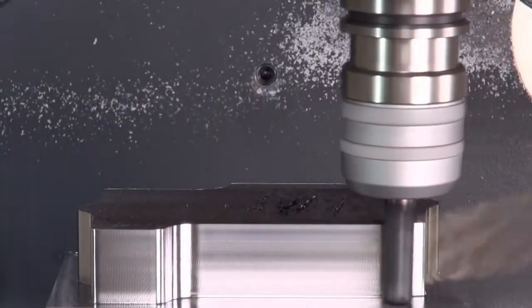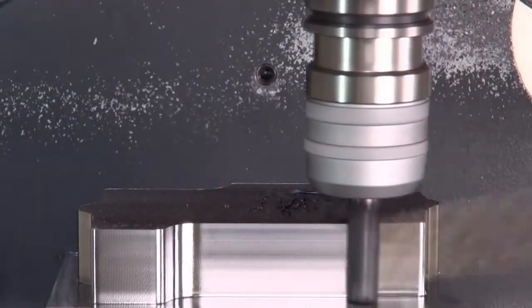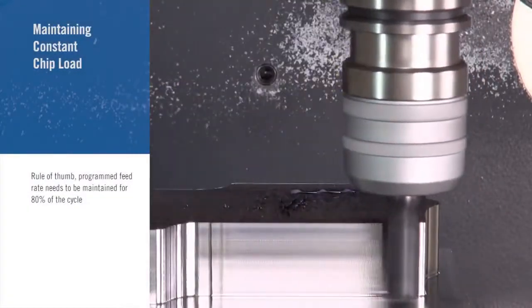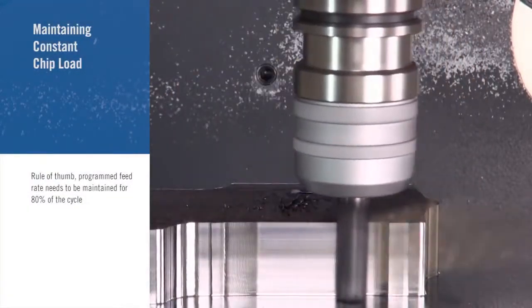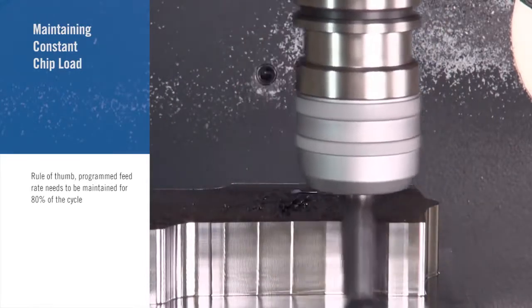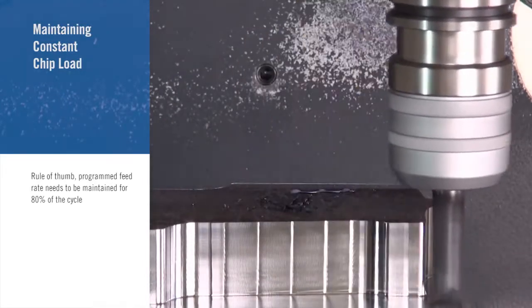Now, maintaining constant chip load is a big thing that I see a lot of people struggle with, and the problem is when you get into high-speed machining, you're using 30, 40,000 RPM machines, you want to run max RPM and max feed rate. But depending on the size of the detail of the part you're machining, that's going to limit how fast you can feed. So my rule of thumb is if you cannot maintain your program feed rate for 80% of the program cycle, you need to reduce your RPM to maintain a more constant feed rate.